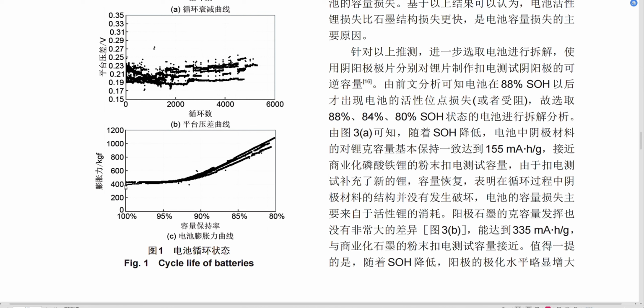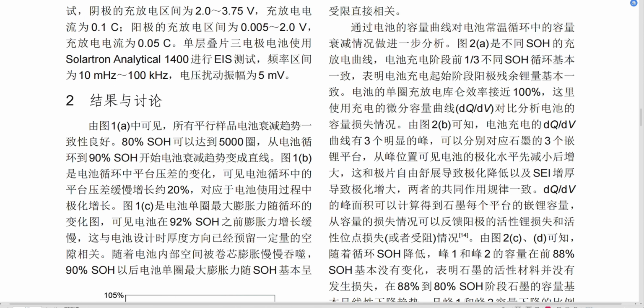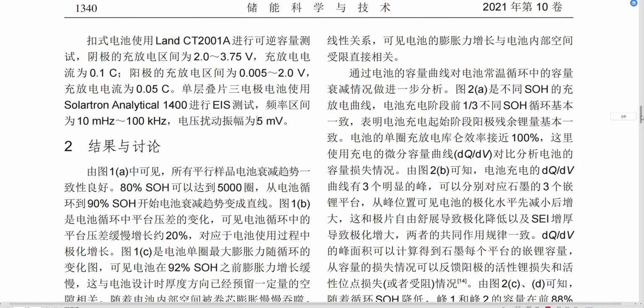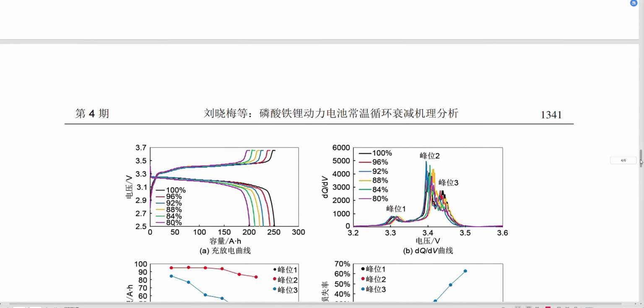Figure 1C is capacity retention versus the maximum expansion force during the cycling. Before around 92% capacity retention, the maximum expansion force doesn't change too much. This is because when designing the cell, there is some buffer for the cell to expand, so you will see a non-change region. After that, the maximum expansion force grows roughly linearly. So this is a summary of this testing.